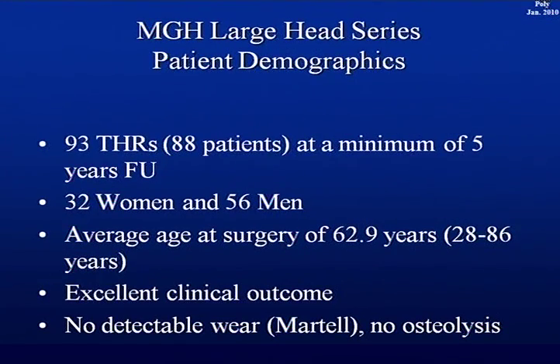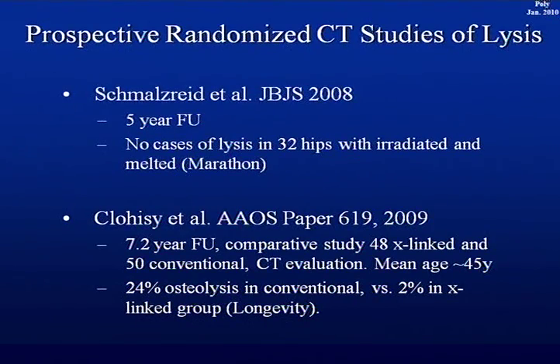We have a large head series as well, which is mostly 36 millimeter heads, close to 100 total hips, and the same average age, around 63 years. Still a very good outcome measured by traditional score systems, and with Martell, what I just showed you, we see the same scatter, no detectable wear, and no osteolysis.